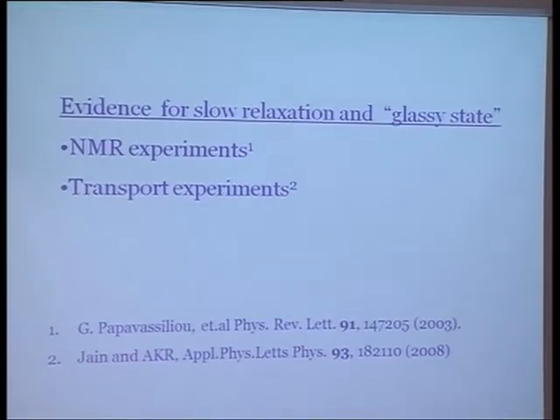Now, as for the glassy state in manganites, there are a couple of previous experiments which give evidence of slow relaxation. One is by a Greek group, and they saw, both from manganese and lanthanum NMR, that as you go to lower temperature, there is a tremendous slowing down of the relaxation time of the spins. And they said at the time, in fact they used the words, that this kind of spin glass state or orbital glass state is forming.